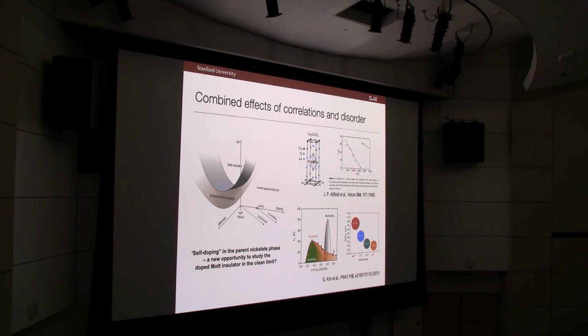So I think some of us heard recently Bernhard Keimer talking about their recent work, where their logic was that by going to lanthanum calcium, that is nominally closer in size in terms of their formal or approximate ionic radius, it has a lower degree of disorder, and compared to the original 214 cuprate dome, let's say with lanthanum strontium, this seems to extend quite a bit higher, and they attribute that to reduced disorder. So again, it's speculative, but we're pretty interested in studying this aspect and using the fact that we can vary the lanthanide series and hopefully change essentially different discrete points on this axis in the absence of solid solution disorder. So this is one of the things that we're pushing on next.